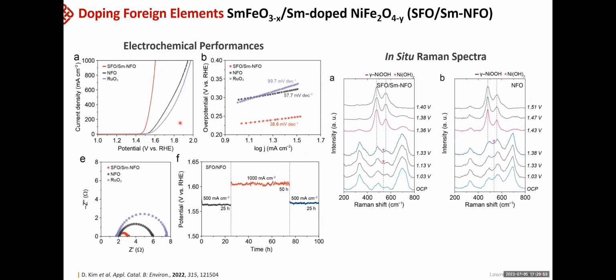And from the OER performance, it shows very good performance with the overpotential of 220. More important thing is we could actually bring the current density to 1 ampere, and it was quite stable over 100 hours. And we believe this is because we have both the interface and the doping effect.